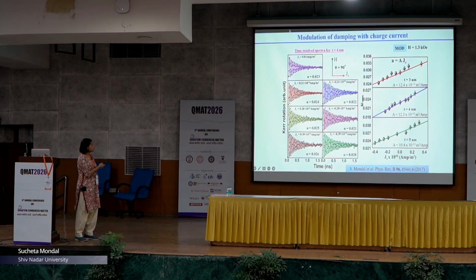Here is the background-subtracted precessional data fitted with the sine formula. You are seeing a plain sine theta variation with an exponential envelope, and that envelope will give us an idea about damping, right. These are plotted with changing Jc, which is the charge current density. For one polarity, which is positive polarity, we will see that the damping is high. However, for the negative polarity of the charge current, the damping is improved, or the profile is improved. We have now plotted those numbers and they fall on a linear trend. This trend gives us the amount of modulation of damping.